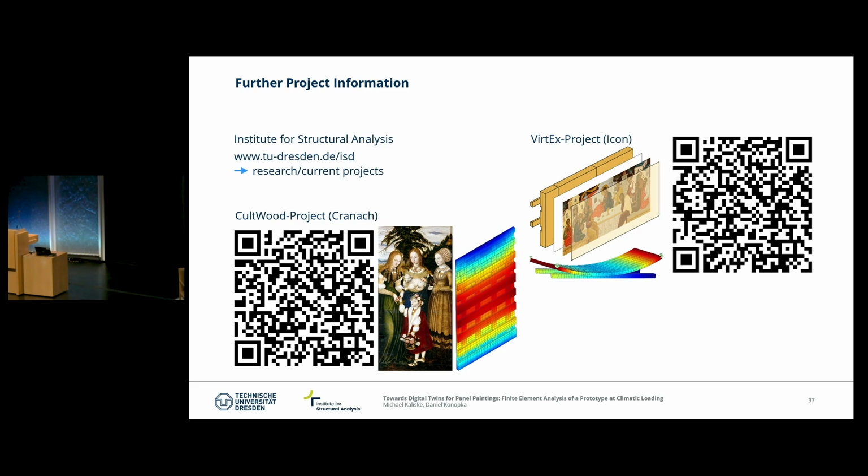And the most common or reasonable explanation is the dynamic response to seasonal changes, which result in a plastic compression of the back of the wood so that it is slightly shrunk compared to the front of the wood. Have you looked at that in terms of your model? It would be very useful to know whether your model will predict long-term curvature, which is irreversible due to plastic behavior.